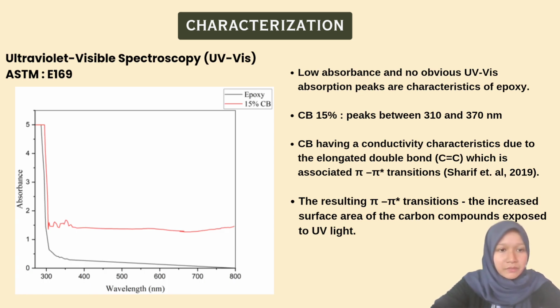In the result of ultraviolet visible spectroscopy, low absorbance and no obvious UV-Vis absorption peak are characteristic of epoxy. The carbon black epoxy composite UV-Vis results show two stretch peaks between 310 and 370 nanometers. It is believed that CB has a conductivity characteristic due to the elongated double bond, which is associated with the pi to pi star transition. The resulting pi to pi star transition is most likely attributed to the increased surface area of the carbon compound exposed to the UV light.